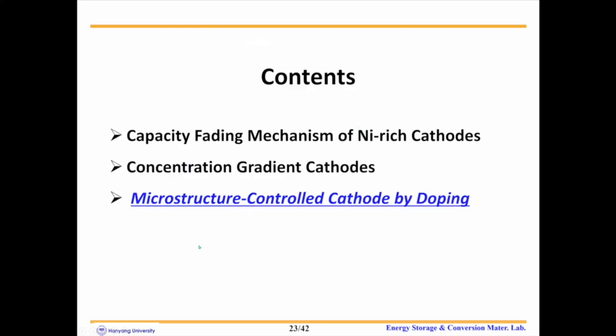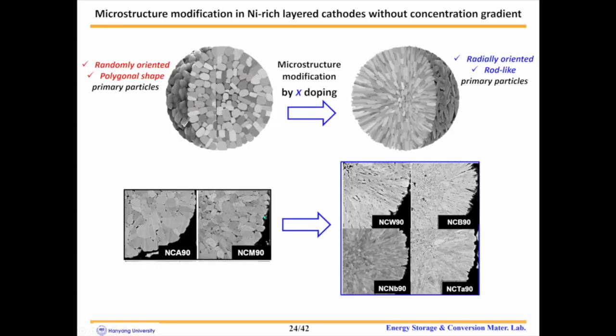I will briefly introduce microstructure controlled cathodes. Inspired by the concentration gradient cathode materials, we modified nickel-rich cathode material without a concentration gradient. The conventional NCA and NCM cathodes are composed of randomly oriented polygonal shaped primary particles, and the microstructure can be modified by dopings. The modified cathode consists of radially oriented rod-shaped primary particles, as you can see here.